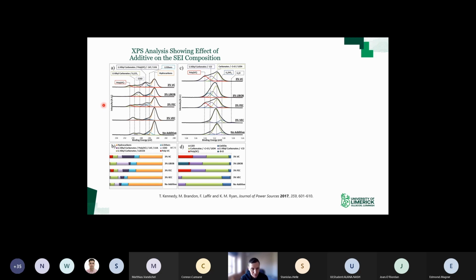So when the silicon expands, the SEI layer is less prone to cracking. If the SEI layer is less prone to cracking, you don't get this continuous deformation and reformation of the SEI layer. So you don't get this continuous decomposition of the electrolyte. Or at least you do get it, but to much lesser extent than for a no additive type material. So the presence of that poly-VC was very, very important.